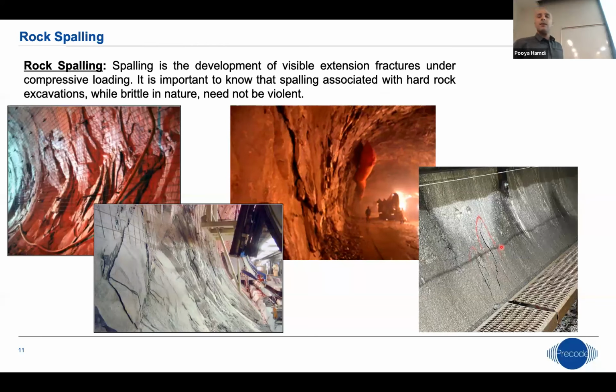So when we are dealing with brittle fracturing, it could be rock spalling, which is a non-violent development of the fractures. It generally takes a bit of time to develop, and it's a self-stabilizing system, meaning that as soon as the confining pressure in the tunnel is sufficient, it stops. In a couple of snapshots here, you can clearly see slabs of rock being detached from the tunnel itself, and then they end up falling to the ground. And here is a really nice example of what we saw in a pressure tunnel in Switzerland, just at the beginning of the development of the spalling itself, on a millimeter scale.